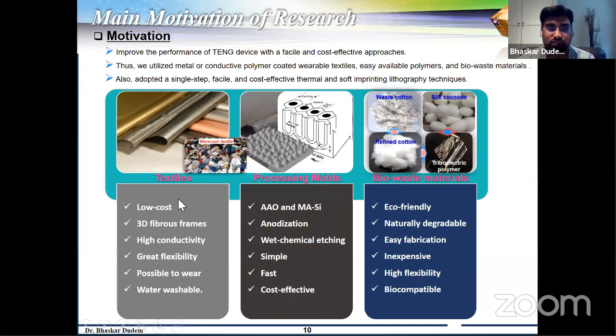First of all, textiles are easily available. In particular, we have used worn-out textiles. Whatever textiles have been used for several months or several years, we have collected and used to develop nanogenerators. Using these textiles, can we reduce the cost? At the same time, the fibrous structures on top of textiles, since it's made up of fibers, can give the micro pattern. As we have discussed, micro patterns on top of triboelectric nanogenerators are advantageous to increase the surface charge density. So the textile itself can be used as a micro pattern substrate or triboelectric material, and it can be expected to increase the surface charge density.